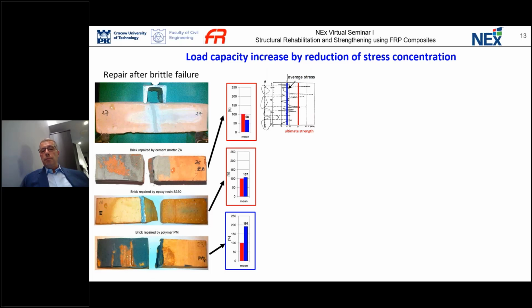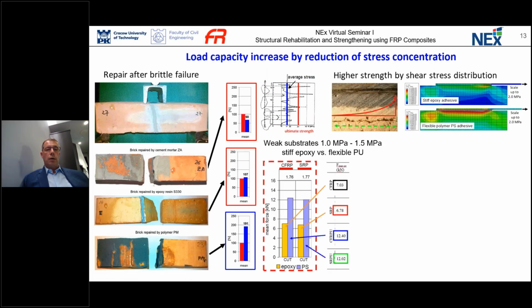Why is it so? Because if we have brittle material and high strength, we have a lot of stress concentrations between gravels, and they can form micro cracks and then link into a main crack. When we rebond it with stiff material, we do not improve the situation. But if we do it with flexible material, we redistribute the stress more evenly, so we are able to increase the ultimate strength.